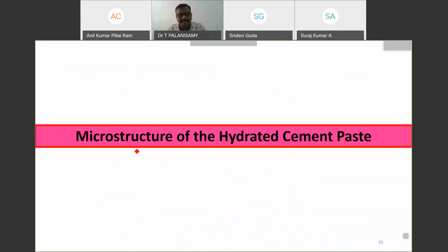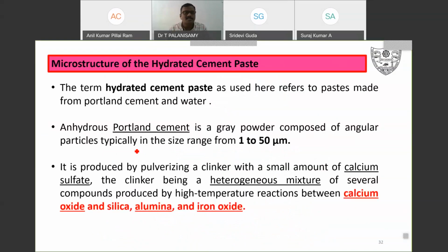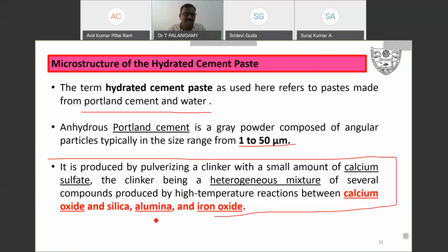Then the microstructure of the hydrated cement paste. The term hydrated cement paste used here refers to the paste made from Portland cement and water. That is called hydrated cement paste. Unhydrated Portland cement is a gray powder composed of angular particles, typically in the size range of 1 to 50 micrometers. It is produced by pulverizing clinker with a small amount of calcium sulfate, the clinker being a heterogeneous mixture of several compounds produced by high temperature reactions between calcium oxide and silica, alumina, and iron oxides. So these are the things happening inside the kiln. Inside the kiln, I already told.